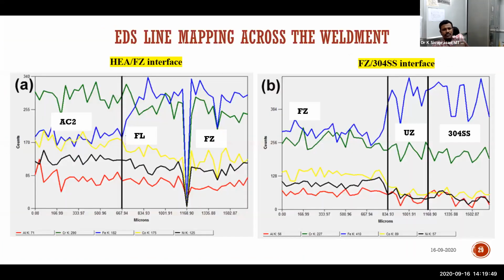The line map we have seen that near the fusion zone, except one location, almost it is a gradual variation, very decent and gradual variation which we have observed. This also evidences that as there is no major chemistry variation from region 1 to region 2, there will not be any stress concentration, metallurgical stress concentration will not be there in these systems. So thereby we are expecting uniform deformation, good strength and ductility combinations from the fusion zone.